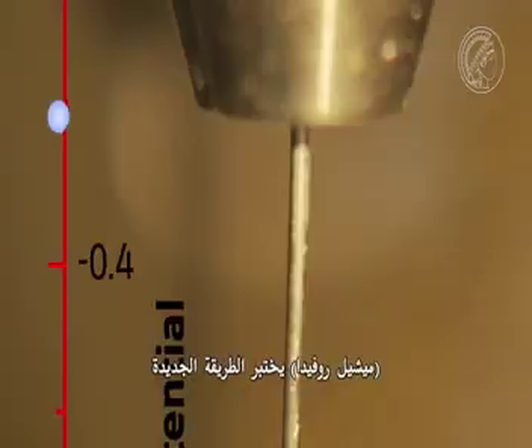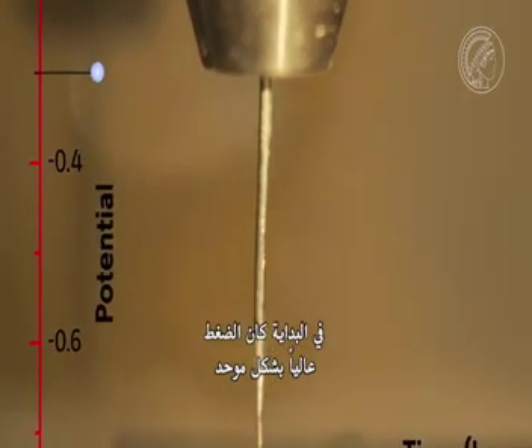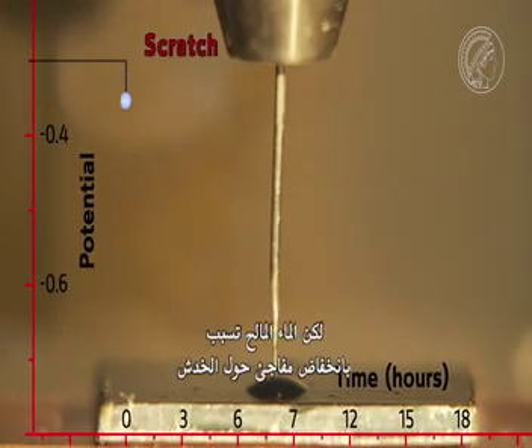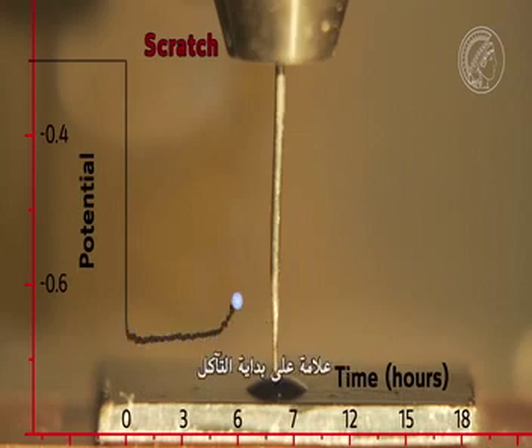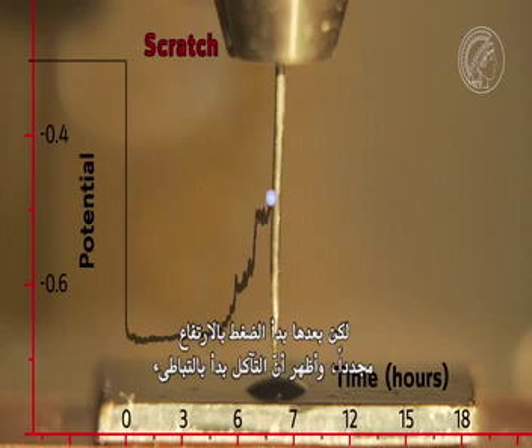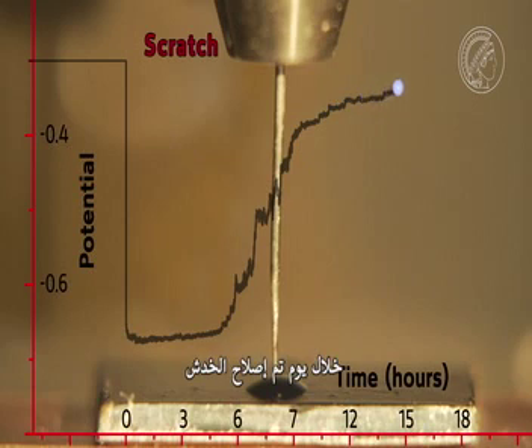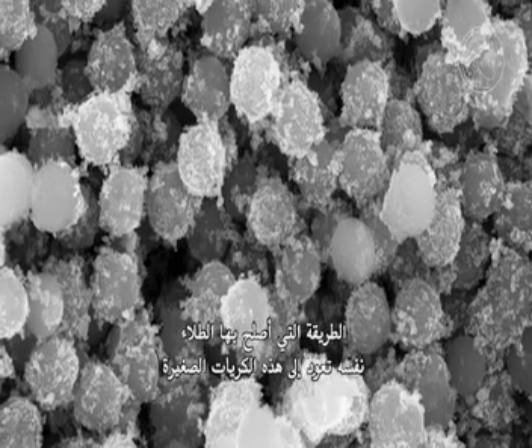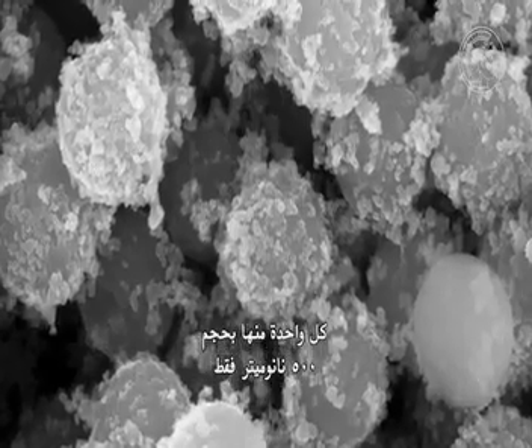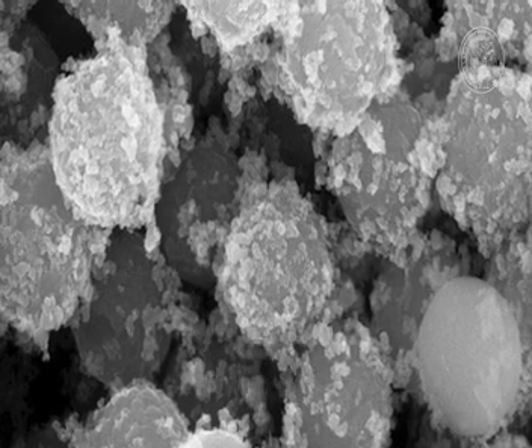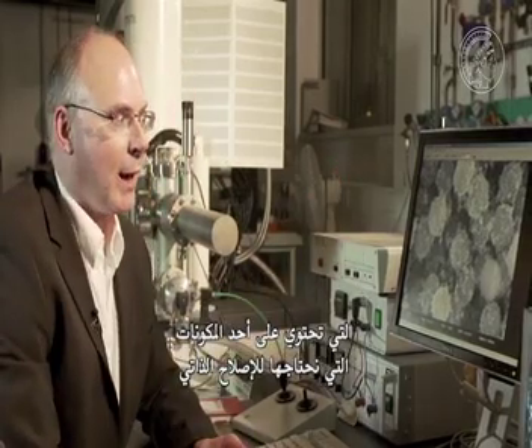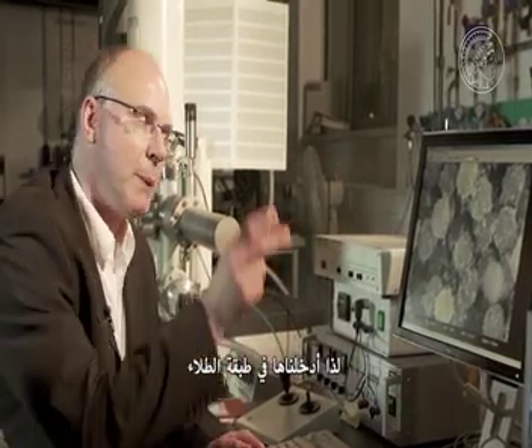Michael Rohwerde is testing the new process. At the beginning, the tension is uniformly high. But the brine results in a sudden drop round the scratch, a sign that corrosion is starting. But then the tension gradually starts to rise again and shows that the corrosion is slowing down. Within a day, the scratch has even been repaired. The way that the varnish repairs itself is partly due to these little spheres. Each one is only about 500 nanometers in size. These are the so-called raspberry particles, which contain one of the components which we need for the self-repair, and so we incorporate them into the layer of varnish.